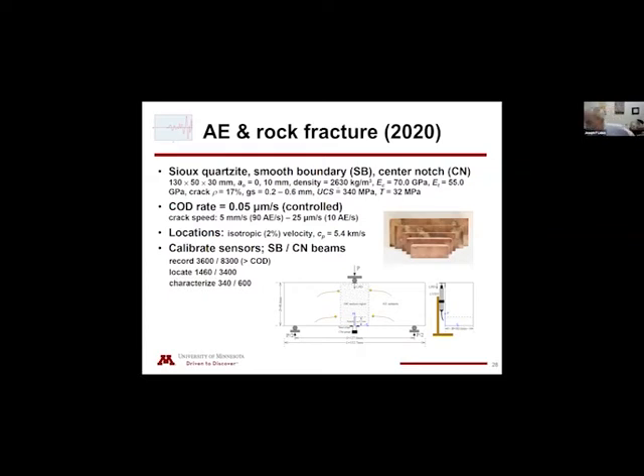This rock is virtually all quartz. The density is quite high, so the specific gravity of quartz is 2.65. We're very close. This material virtually has no pores, only cracks. So the Young's modulus in compression is this value of 70, whereas in tension, it's 55. And if we assume a random distribution of penny-shaped cracks, we would estimate a crack density of 17% based on these parameters, these numbers.